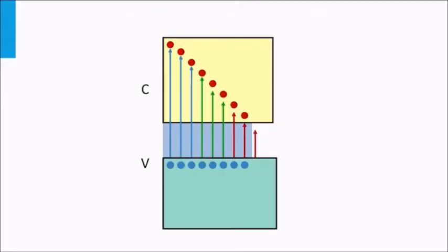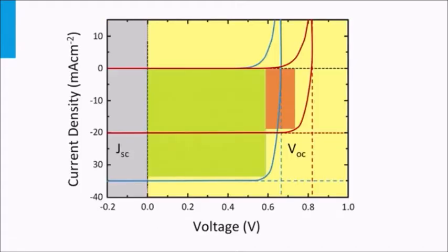If we now consider an absorber material with a lower band gap, we see that more photons in the spectrum can excite charge carriers. This material will result in large short-circuit current densities. However, due to the smaller band gap, the splitting of the quasi-Fermi levels and the resulting open circuit voltage will become smaller. This is reflected in the blue JV curve.